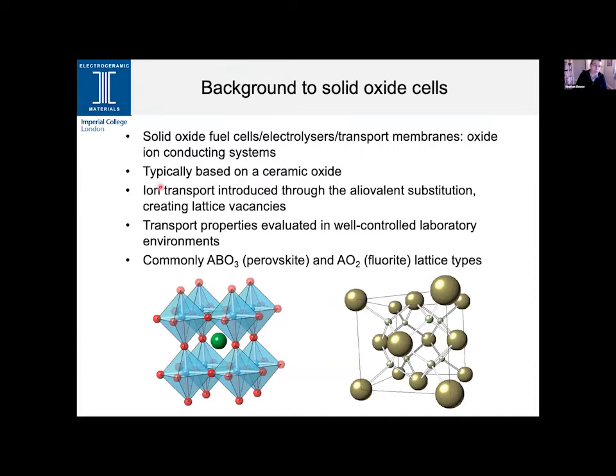And in this case, the ion transport, in particular, we're looking at oxide ion transport, is introduced through the aliovalent substitution on lattice sites. That creates those lattice vacancies, giving the oxygen mobility within those particular materials, and operating essentially at elevated temperatures. So we're looking at operation from temperatures greater than 500 degrees C up to around about 1000 degrees C.